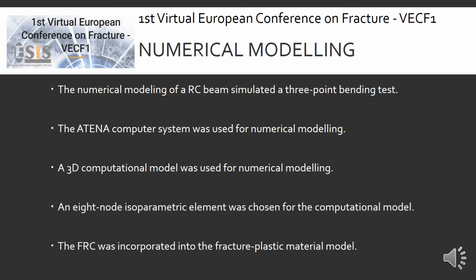Now to the part on numerical modeling. The numerical modeling of the reinforced concrete beam simulated a 3-point bending test. The ATENA computer system was used for numerical modeling. A 3-dimensional computational model was used, and eight-node isoparametric elements were chosen for the computational model. The fiber reinforced concrete was incorporated into the fracture-plastic material model.